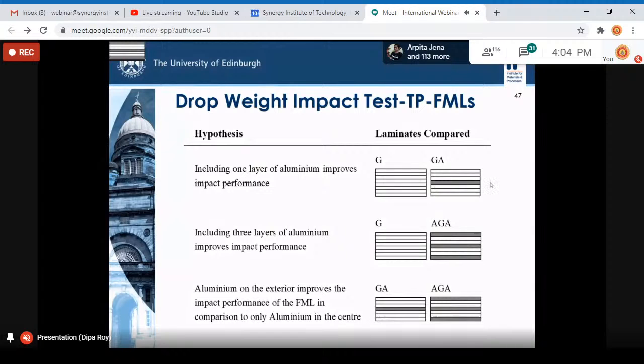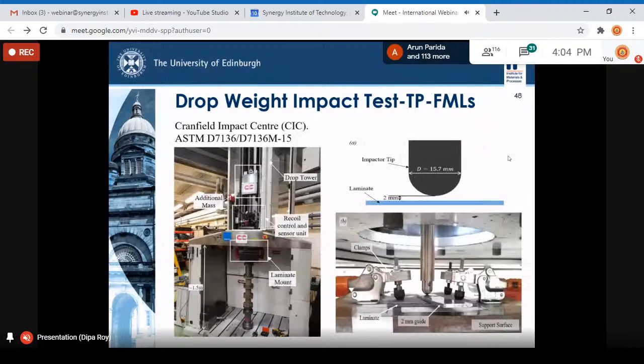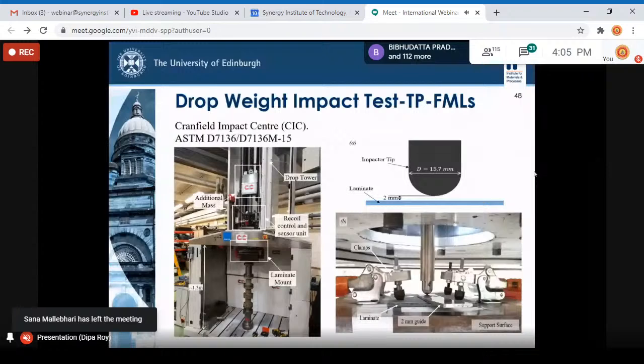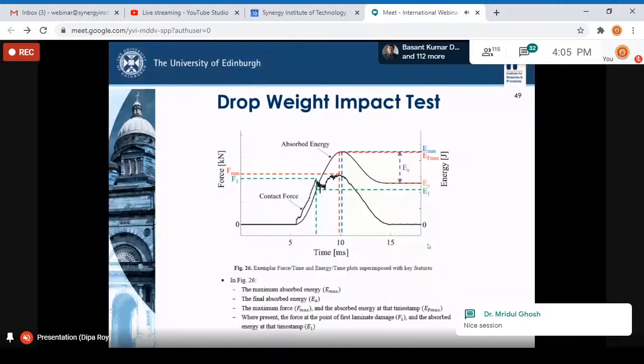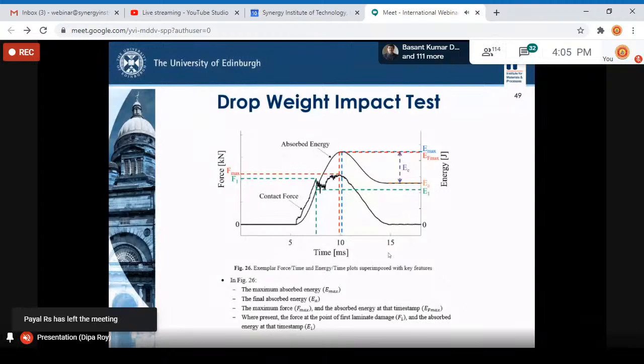So these are some of the experimental plans we made, and we used a drop weight impact tower at Cranfield University. They have a very big impact center with many drop weight impact towers. We used one of them. This is how the indenter, the impactor tip, looks. And this is the standard process of drop weight impact, following an ASTM standard.